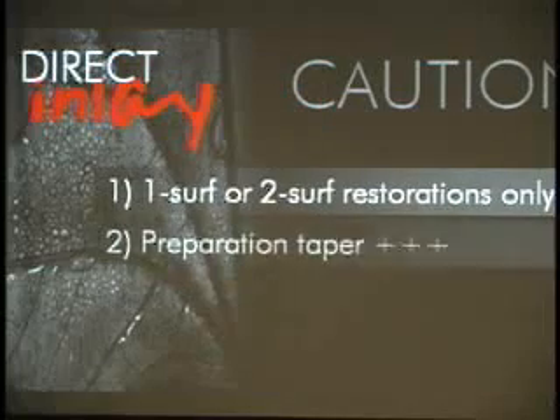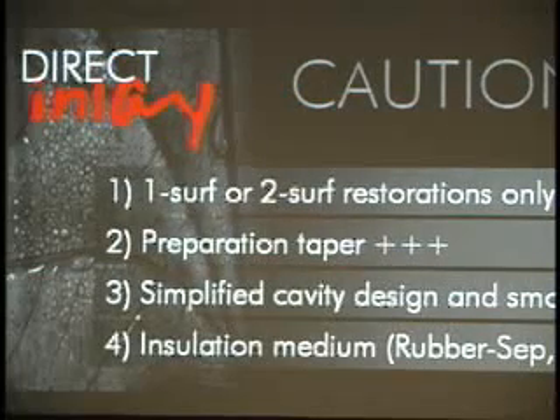What is obvious today is that clinical studies could not really show if the post-curing is really essential. So basically, the semi-direct technique is useful to allow this initial big polymerization shrinkage to happen freely. For sure, that helps. Now, whether the post-curing is really determinant for the clinical performance, we don't really know.